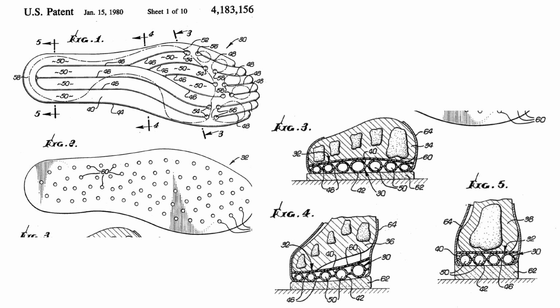6. The material should not contain plasticizers or other materials that would migrate from the material in service and cause toxic reactions with the skin, degradation of the properties of the material, or damage to adjacent parts of the article of footwear in which the insole is incorporated. 7. The material should have excellent resistance to relaxation and stress when subjected to continuously high tensile forces. 8. The material should have excellent elastic deformation and recovery characteristics without permanent set.